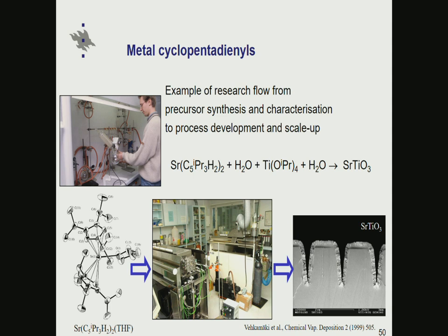Our work on cyclopentadienyls really started from a process for strontium titanate, in the late 90s. We were requested to develop an ALD process for strontium titanate, which is a very high-K dielectric. There were several good processes for titanium oxide available at that time, but for strontium we didn't have good choices. There was only strontium THD, but that wasn't reacting with water, and if we were using ozone, carbonate contamination was a risk, and that's why we came up with the idea to test cyclopentadienyls there.